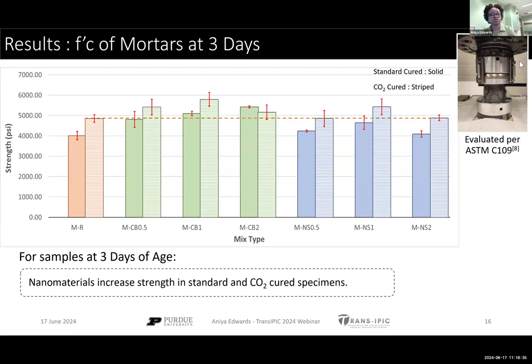Furthermore, when we're looking at our CO2 cured samples, we're seeing that nanosilica actually kind of decreases our strength in reference to our reference sample. However, at 3 days, not nearly as much. Nanosilica at 1% still improves the strength. And then for our carbon black samples, we're seeing an overall increase in strength as well. So we can generally say that nanomaterials increase strength in standard and CO2 cured specimens. Generally, we're seeing about the same, if not a little bit higher, increase in strength.